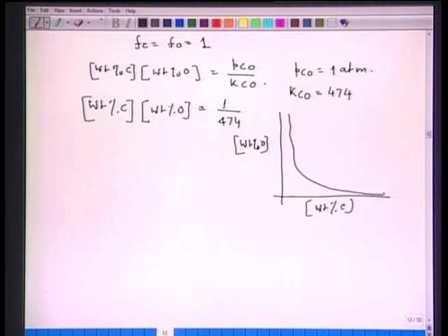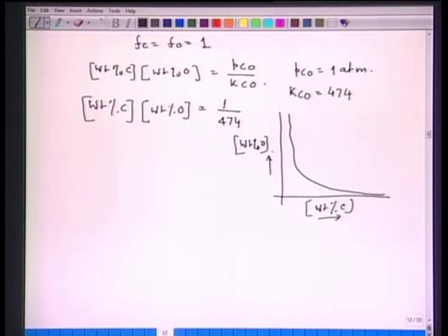This is just a schematic relationship. So, weight percent carbon increases from here and weight percent oxygen increases in this direction. What this plot suggests is that as the weight percent carbon increases, the weight percent oxygen dissolved in steel decreases. Also, this plot suggests that at low percent carbon in steel, the dissolution of oxygen increases, because if you see at the lower ranges of carbon, the dissolution of oxygen increases very fast.